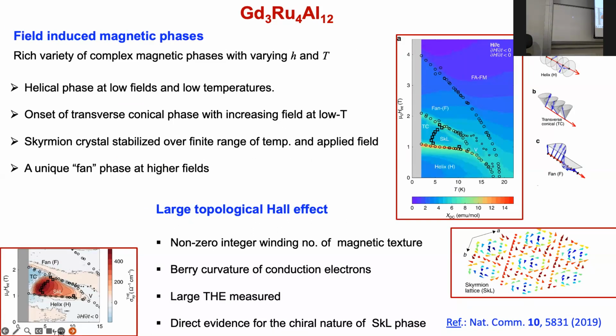And this is the full field-induced phase diagram as you vary the applied magnetic field and the temperature. You go through a host of very interesting phases. At low values of the field over a wide range of temperatures, you form helical order. That is what we said, below 17.2 Kelvin you form a helical order. As you keep increasing the magnetic field at low temperatures, you enter what is called a transverse conical phase, where you induce this non-coplanarity, but you still don't have fully formed skyrmions.